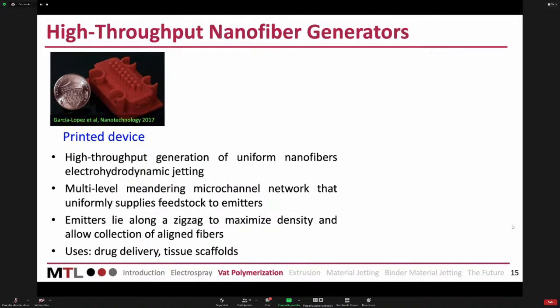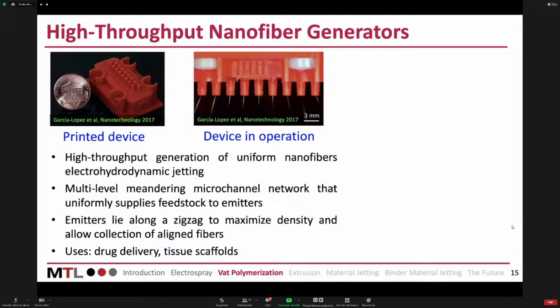So this is a nanofiber generator. You cannot see it because it's an opaque resin, but it has a fairly complex network of channels that is supposed to regulate and uniformize the liquid inside. So this is going to use these polymer melts that generate nanofibers. But at the end, if you design it well, then you get this thing to work uniformly.